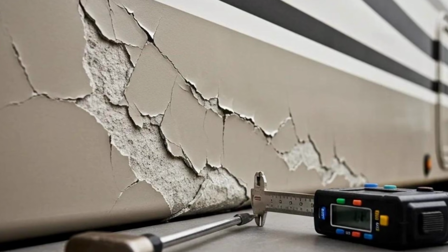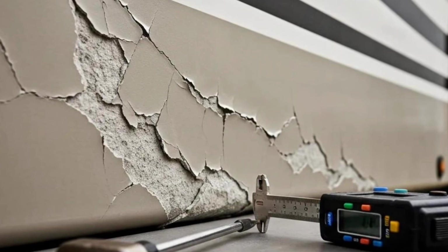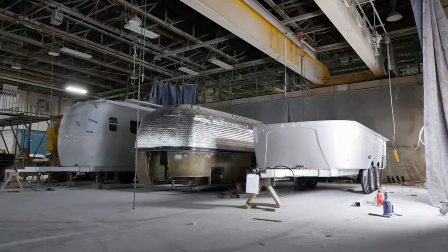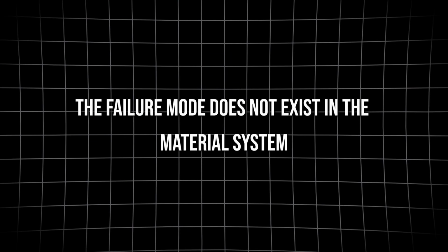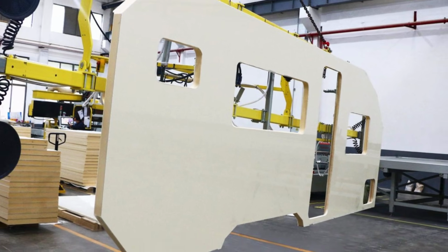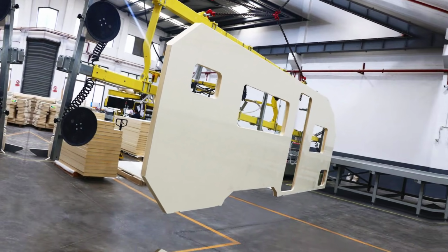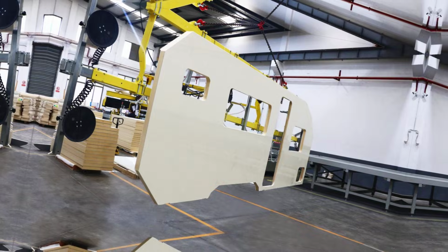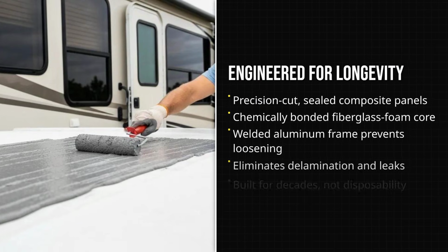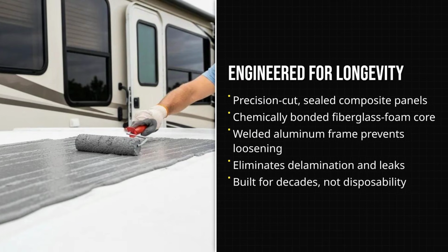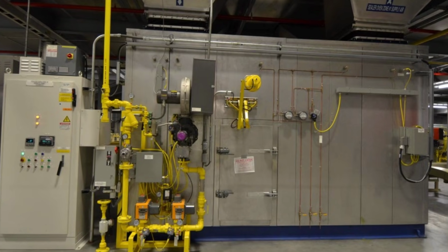You cannot separate the skin from the core without destroying both. This is why Oliver trailers do not delaminate. The failure mode does not exist in the material system. The assembly process for composite panel construction is slower and more expensive than stick building. Each panel must be precisely cut, the edges must be sealed, and the panels must be bonded to the frame with specific cure times and temperature control.